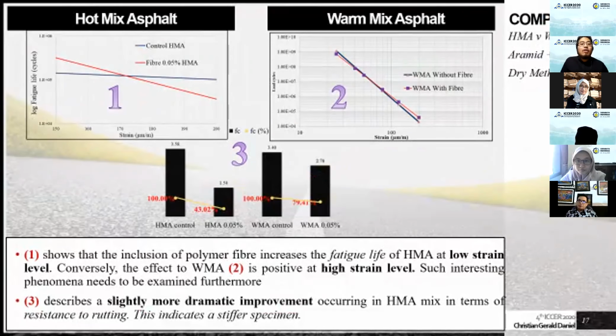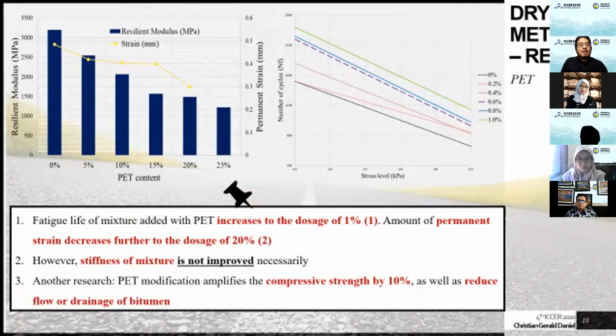And if we try to compare the performance of RAP in hot mix and warm mix, the result is in contrast. You can see that the fatigue life of the mixture is increasing at high strain level for warm mix, whereas it was in contrast with the fibre hot mix asphalt. And this is the result of PET within the dry method.